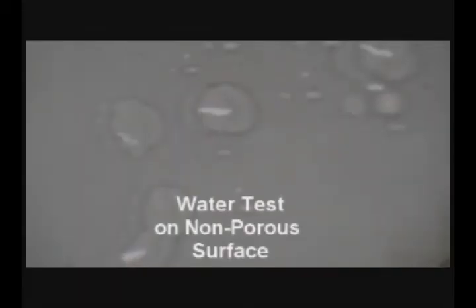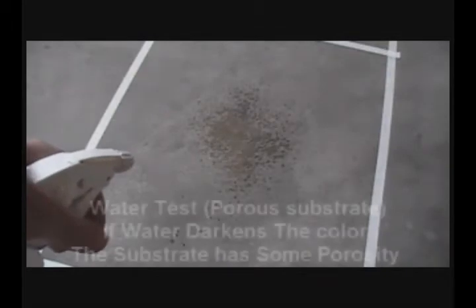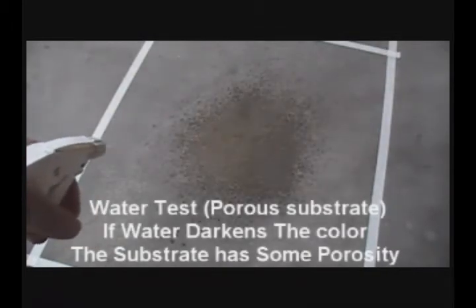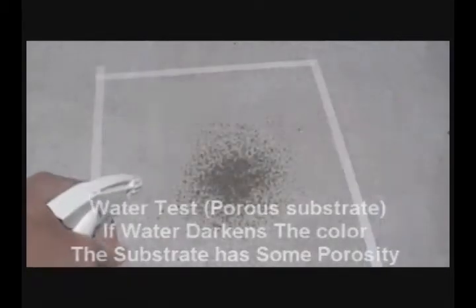Let's try a water test on a non-porous surface. Water can't penetrate the surface, so it beads up and will remain on top until dry. A water test on a porous substrate shows if water darkens the color, the substrate has some porosity.